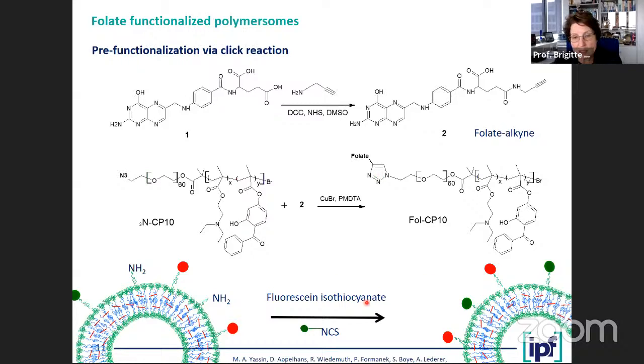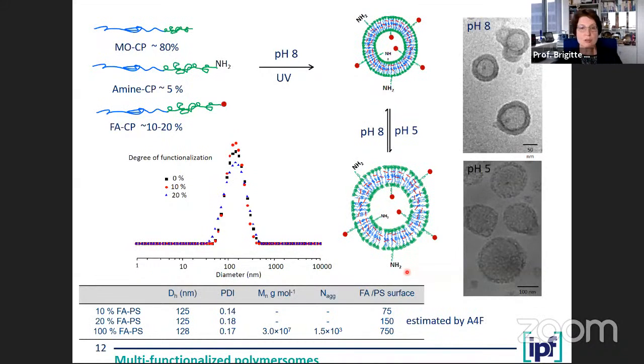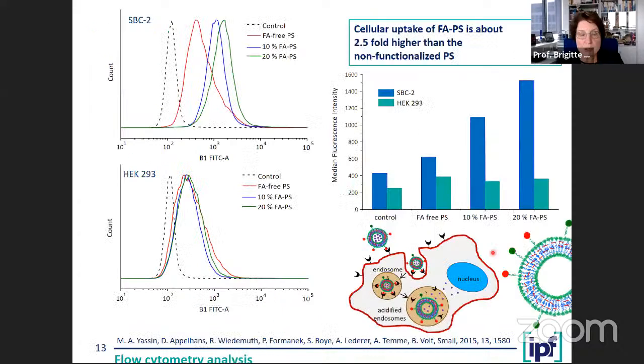And we introduced, in addition, also a marker which allows us to follow our nanomaterial in cells, for example. So the assembly process works also with functional material. When we had the functionality at the chain end, it worked well. We actually made the PEG a bit longer so that the functional groups, especially the targeting groups, really stick out, so they are very much available for targeting. The assembly works very well, no matter if we have the folate onto it or not. You see the capsules, they are robust, and you can do the switching several times, no problem.